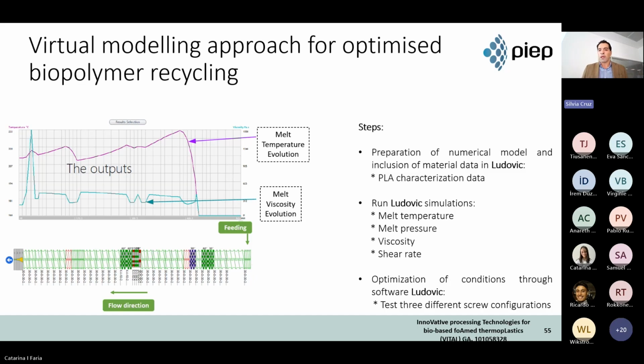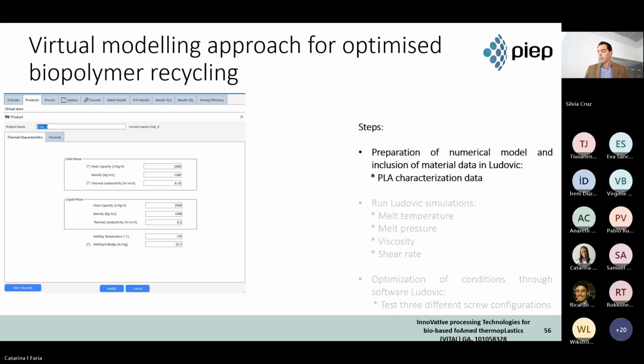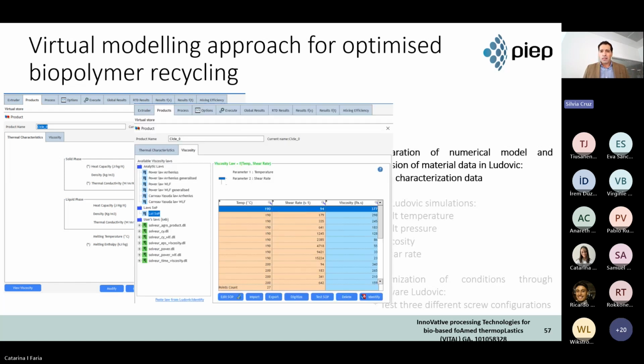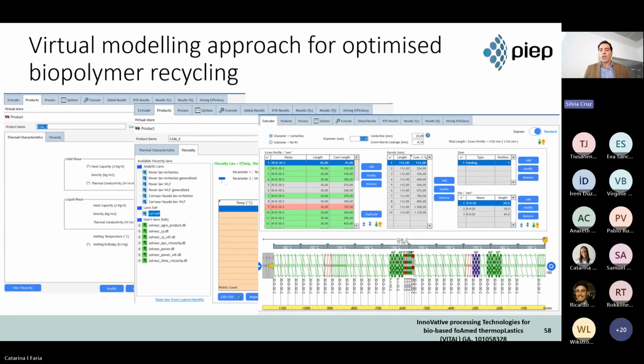I would say the three main steps were the preparation of the numerical model. We need to feed the software with the PLA characterization data. Then we run the simulation to get all the data on the material, and then in the end we can optimize both the parameters and the screw configuration. So the first step was previous characterization of the PLA. Then we feed the software with the thermal data from the material. The second step was to have the viscosities and the temperatures of the material that we want to run the simulation. And then in the end we adjust and try to identify the best processing parameters to run the simulations.